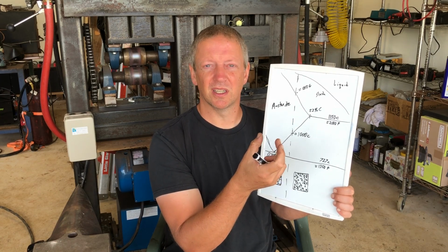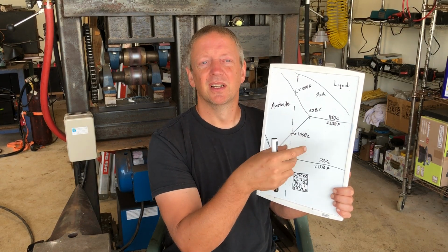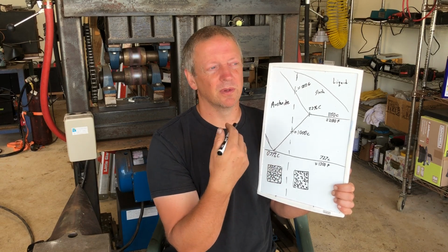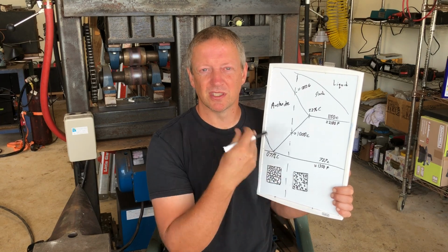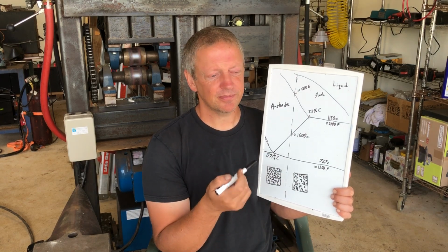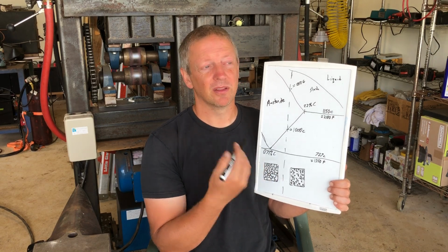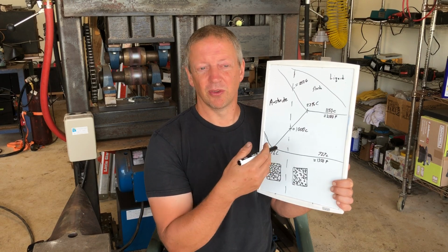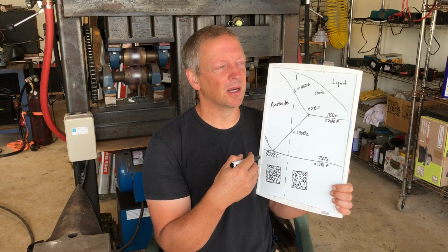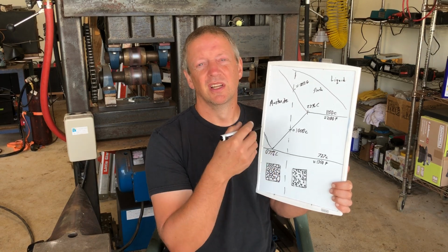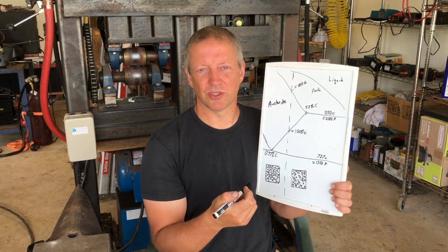Really slow solidification, you'll get one or two very large voids in the center, but for the most part with Wootz ingots, what you get are microscopic voids scattered throughout. These tend to be right in the same areas where you would form these primary carbides. Those are the IDRs, as Verhoeven calls them, or interdendritic regions. They're the last areas to solidify, therefore that's where the pores show up.